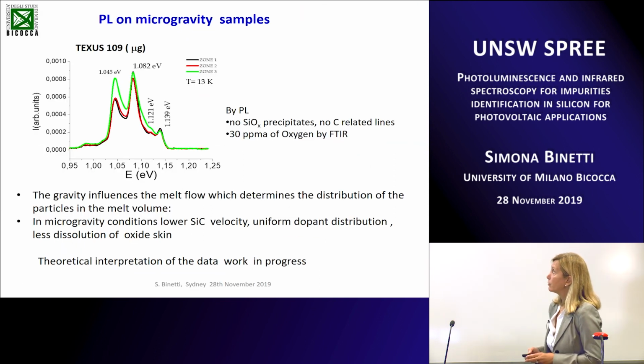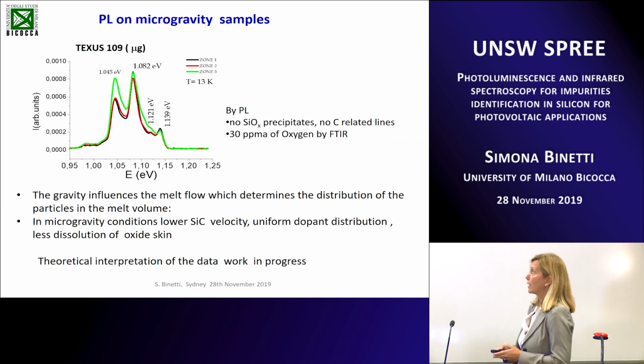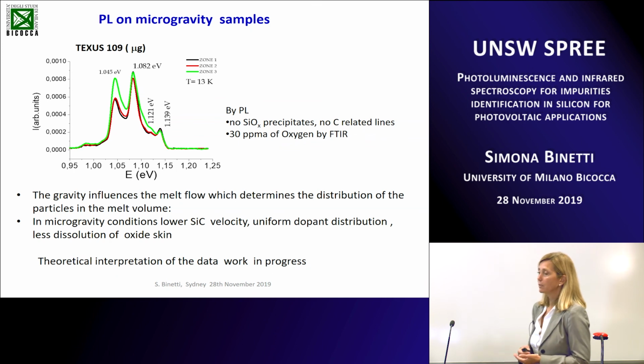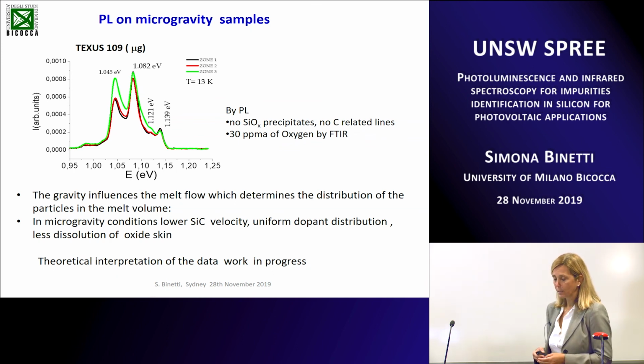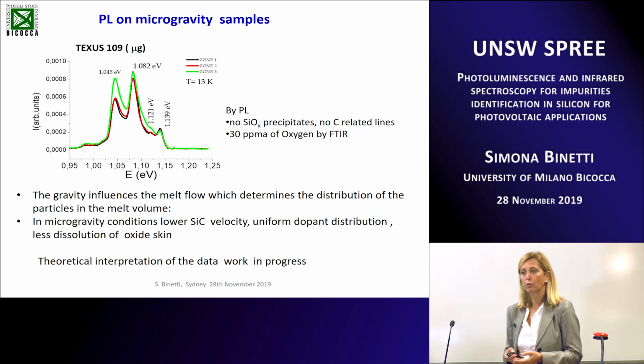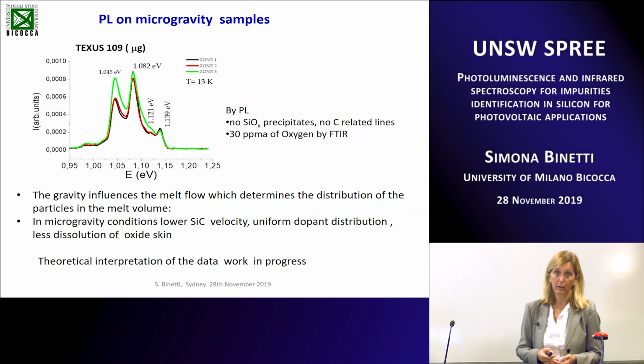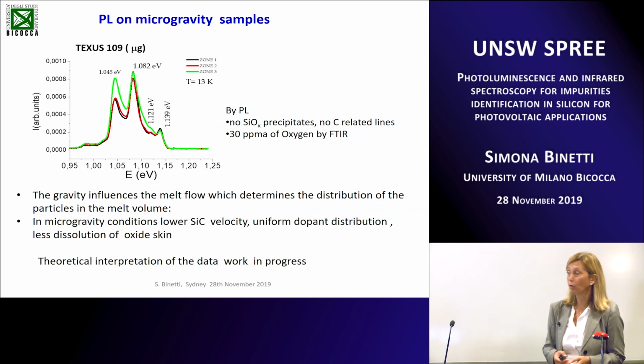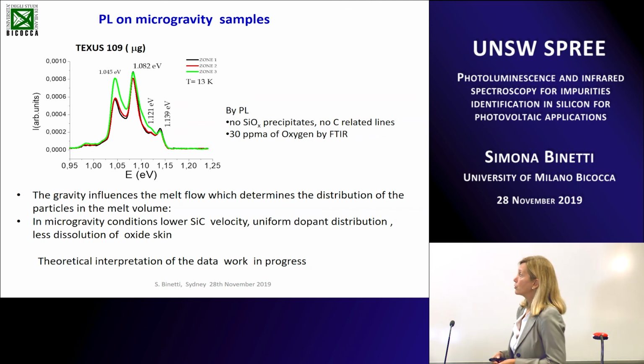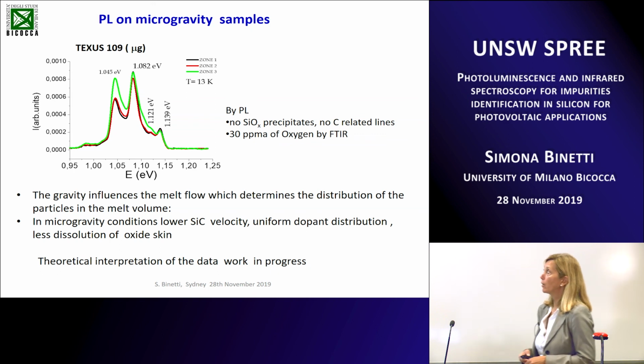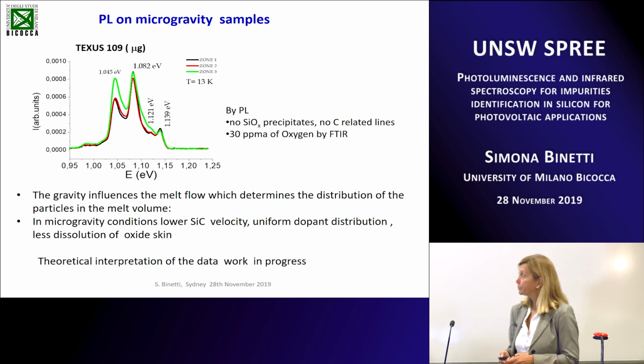As far as photoluminescence is concerned, we have seen the signal related to the dopants, and we have seen that there is a uniform distribution of the dopants. It seems that the segregation coefficients of boron and the dopant are different in microgravity condition than in the normal condition. And also we have seen that we have just small, no silicon dioxide precipitates, even if also in this case we have a very high concentration of oxygen in our sample.